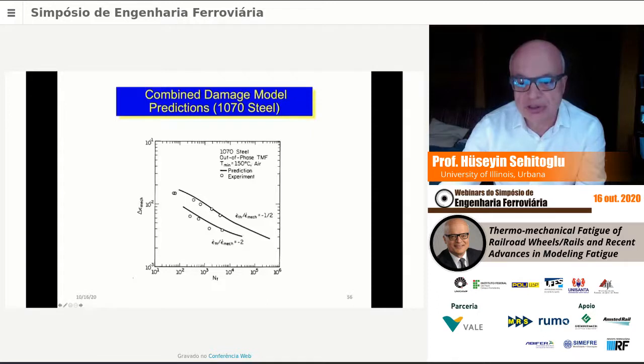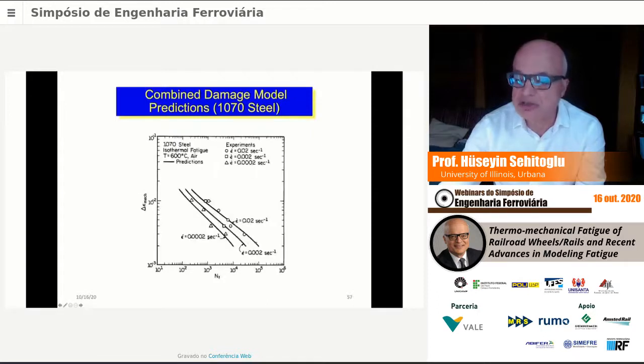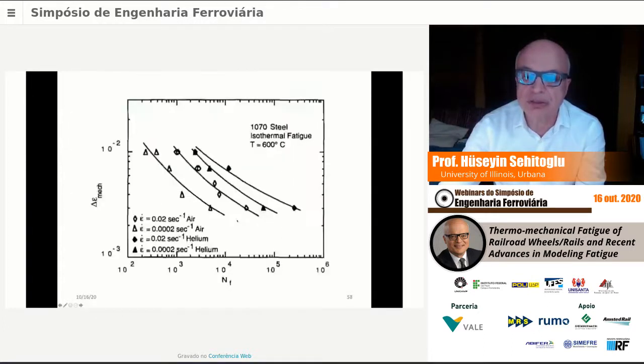And you could see these are different out of phase cases, right? Minus a half means the thermal mechanical ratio is minus a half, minus two. They're both out of phase here. And the predictions are pretty good. This is the isothermal case. Slower rate, shorter fatigue life. Higher rate, longer life.